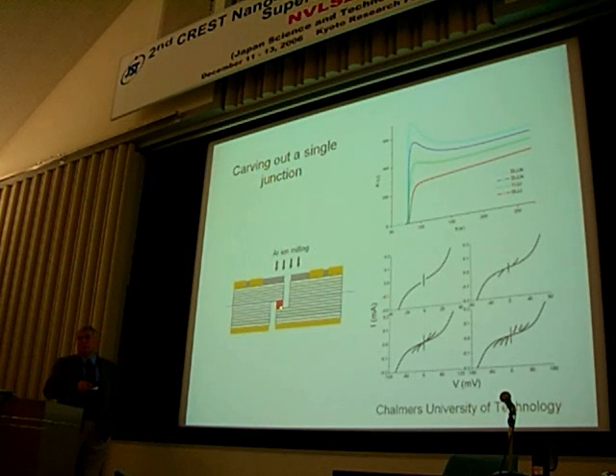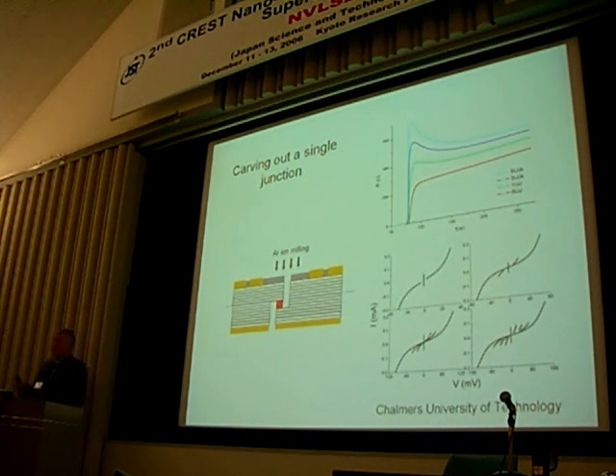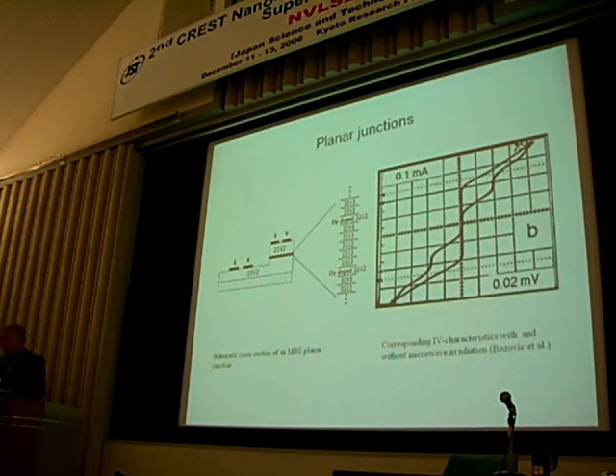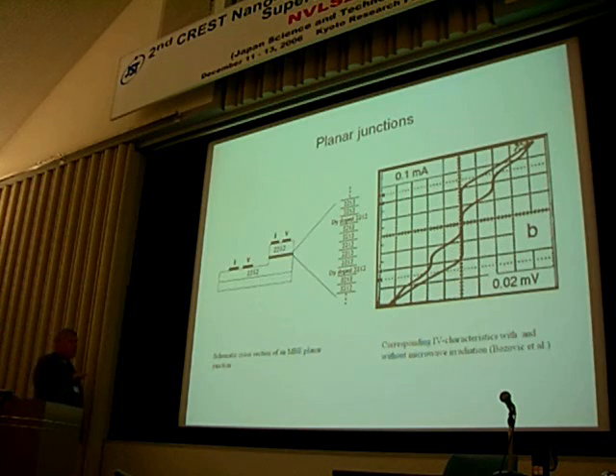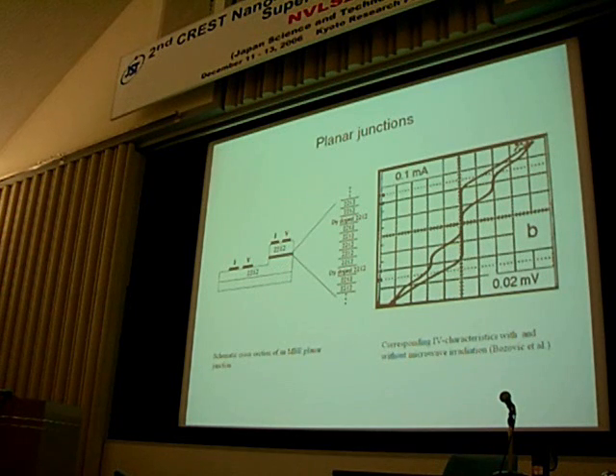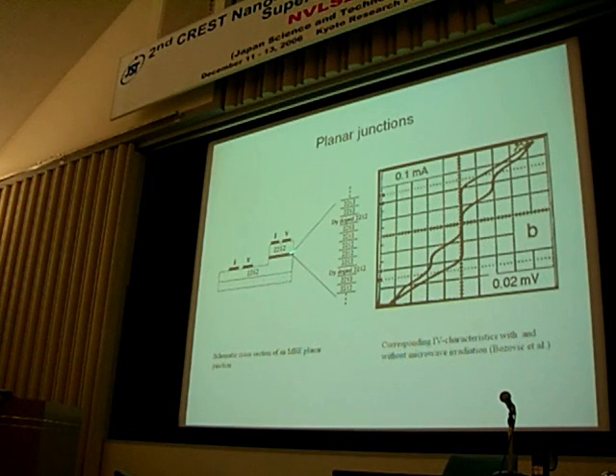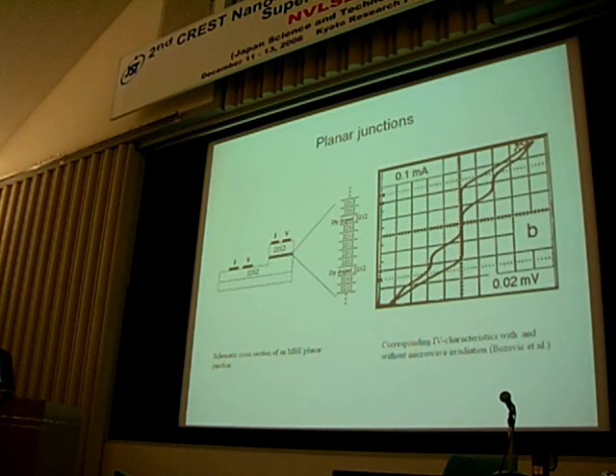Again, it's not easy to prepare. You get one, two, or three or whatever junctions, and for sure not a technology to make a really big circuit. Now, that's quite interesting: if you have an MBE machine, or just a very nice layer-by-layer deposition machine, you can deposit these layers in an atomically flat way. This is something which was actually done. And here, in this case, for bismuth compounds, you can artificially make these junctions, where you have a superconducting layer, a tunnel barrier in between, and another superconducting layer on top.